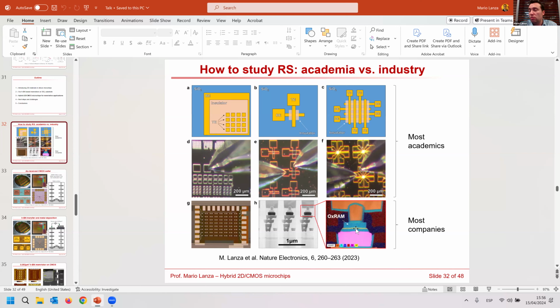We have used gold, we have used titanium, we have used silver. One of the reviewers of our Nature paper was very annoying, saying, "No, but you use gold. This is not a CMOS compatible material." We use gold because it's the one that allows us to switch best. We cannot use titanium nitride because titanium nitride requires a special recipe to have a very good conductivity. There are not many works in academia using titanium nitride.